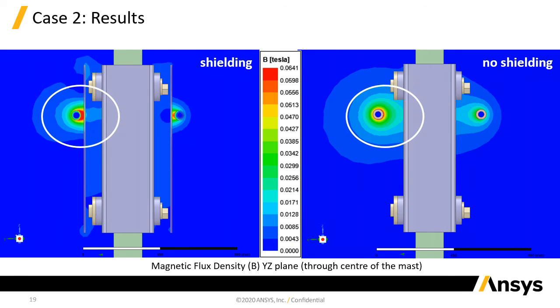So if we look now at the B-field plots, on the left-hand side we see the B-field contour plot for the design with shielding for case 2, and on the right-hand side we see it for the option where there was no shielding, just so you can compare the intensity of the field, and you can see quite dramatically how this, just a simple aluminium plate, really just blocks off the field from reaching the carriage. So there's a strong interaction between the bus tube and the aluminium plate itself, and that prevents the field really from passing past the plate and to the carriage. Okay, so you can see just even visually we get quite a significant shielding effect there from these plates.